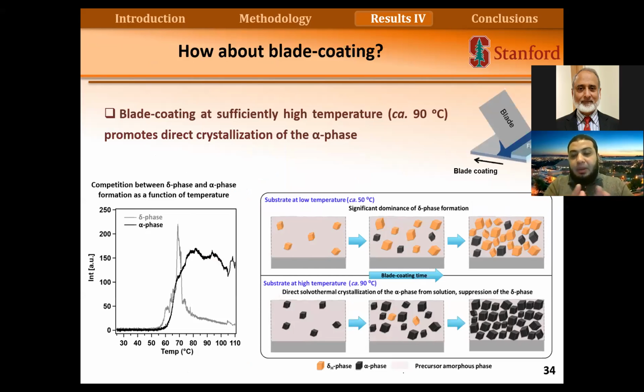So we tried also to apply this into blade coating. The previous study was spin coating, and after spin coating, we were doing annealing. So we tried to compare this to a technique that can be applied for scalable fabrication. So again, here we use the blade coating. The blade coating is a technique that can be applied by roll-to-roll processing and can be used like printing papers. We try to understand the competition between these phases at different temperatures.